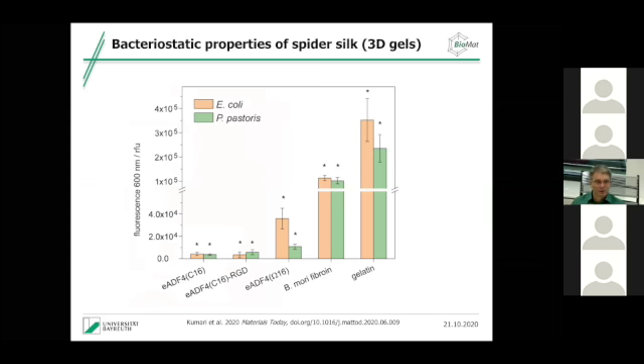Now let's go back to our bacterial story. So I showed you that the surface of the silk is microbe repellent. How about now in the hydrogels? Because if you have a bacterial manifestation here, that could also be very severe. And you can see very nicely that, again, our spider silks, and here you see our workhorse, the workhorse with RGD, they actually show no bacteria or yeast manifestation. In contrast to gelatin, which is very often used in 3D printing and biofabrication, and Bombyx mori fibroin, so silkworm fibroin, that does not have these repellent features.